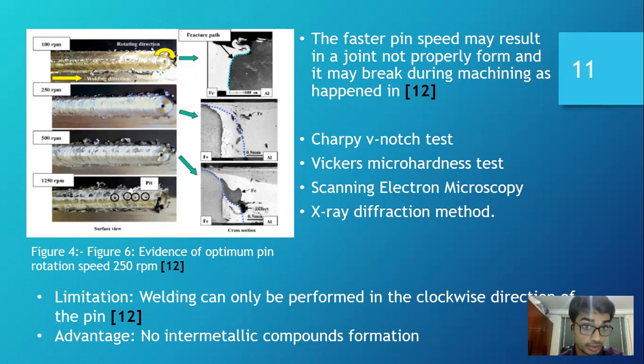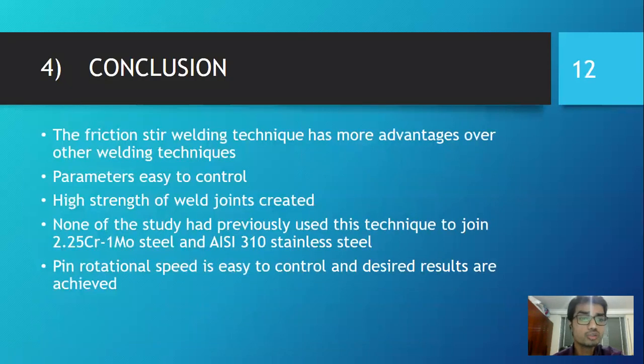However, there are many advantages of this research or this design using friction stir welding, such as there will be no intermetallic compounds formed, and I can alter welding parameters to get a desired quality of high strength welded specimen. So in conclusion, friction stir welding technique has far more superior advantages over other welding techniques, as its parameters are easy to control and can create high strength weld joints. The disadvantages of it are not very related to the strength of welded joint, and none of the previous researchers have used this technique to join 2.25 Cr 1 Mo steel to AISI 310 stainless steel. And I can easily say that this welding will give us much better results than other welding techniques.